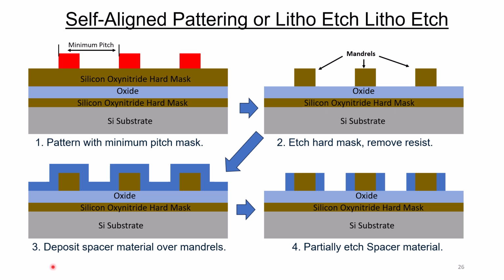So this next technique is called self-aligned patterning. And the way it works is, now you have a silicon substrate, but we've stacked up a couple of layers, maybe a couple of hard masks with an oxide in between. And now we go ahead and we bring in our photoresist with minimum pitch. We define the photoresist, we etch the photoresist, and we use that pattern to etch down into the first hard mask, and it creates this structure to the right over here. And we're going to call these structures that were left mandrels.